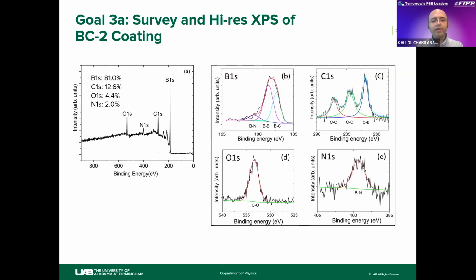So the first figure was for BC1. Now here the same thing happened for the BC2 coating, which is the highly crystalline one. As you can see, this is the boron-rich material, and we have carbon of around 12.6%, and it is also bonded to carbon as a BC bond, as you can confirm from the high-res B1s and high-res C1s.